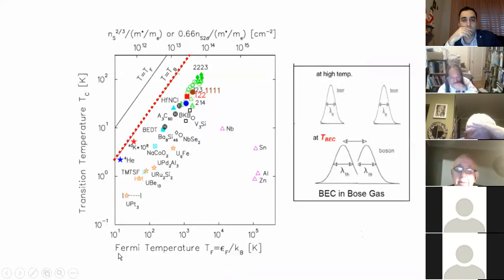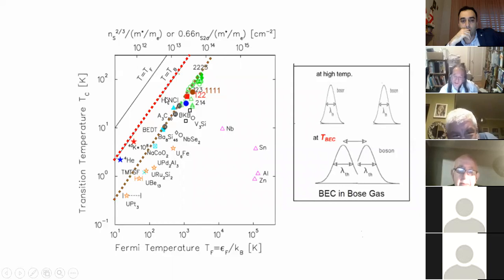Okay, but one still missing piece of information is that this is not simple Bose condensation in the new materials, because the condensation or the superconductivity doesn't happen at this red dotted line. But in these new superconductors, the actual superconductivity seems to be happening in this line about 4 or 5 times lower. But as I mentioned, there are two already measured phenomena, which are the transient or dynamic Nernst response, that are showing up in this red line.